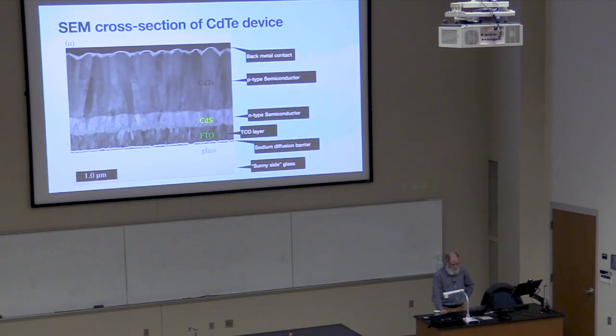And you can see down here, these are like crystals that grow up. So this is a polycrystalline material, as is the cadmium telluride. You can see that structure in there, and that's what makes for good performance in those devices. The other thing this highlights is that, although I listed like 5 layers, there are more layers shown than talked about, because there are a lot of things you need to do to ensure good adhesion or good electrical contact or whatever.